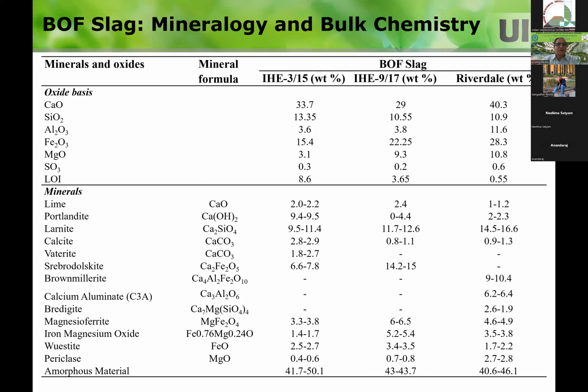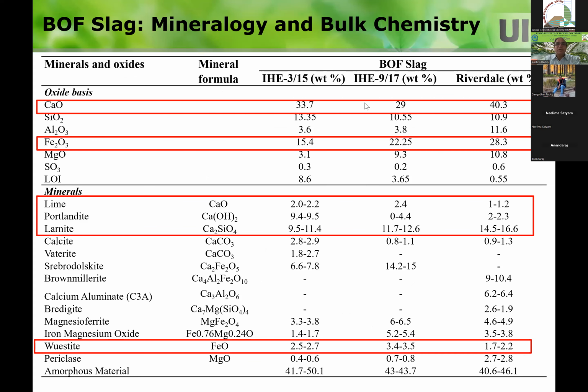So oxide bases and minerals, you can see all these things. What I'm showing you here is that we got this BOF slag from 3 different steel plants, at different times, and Riverdale is another steel plant. The main important thing is we are trying to rely on calcium. Slag is the source of calcium, and also iron, to sequester the H2S. So the most important thing to look at is where the calcium is going to come from: the calcium oxide, lime, portlandite, and larnite. So you see which minerals you have, how much they have, and what is the potential for making calcium or iron available from them.